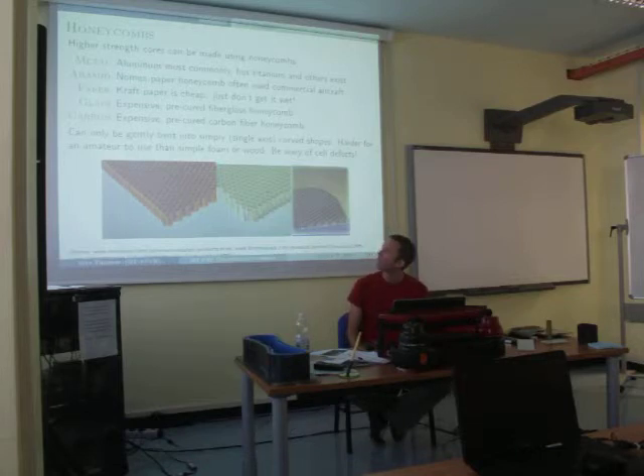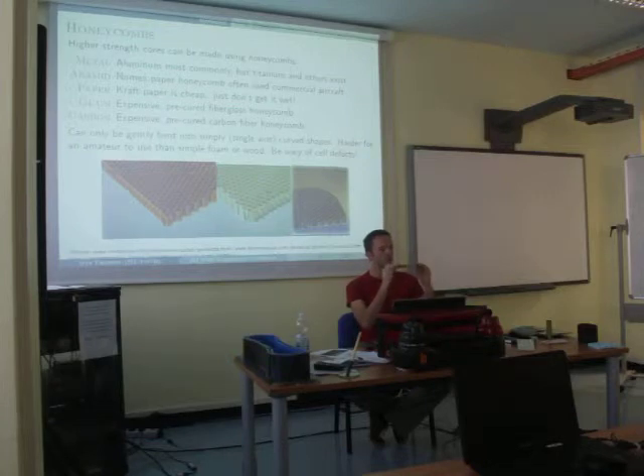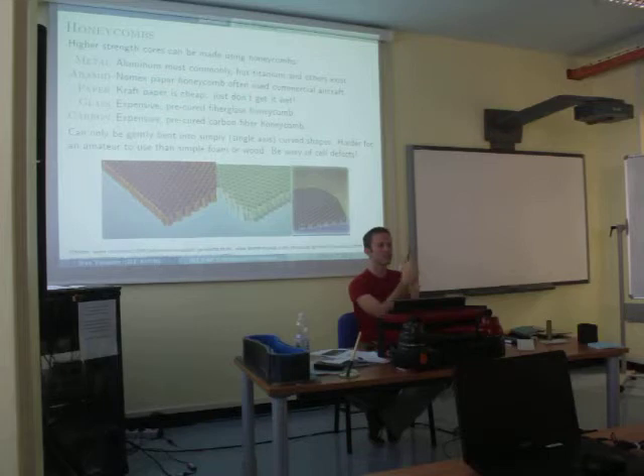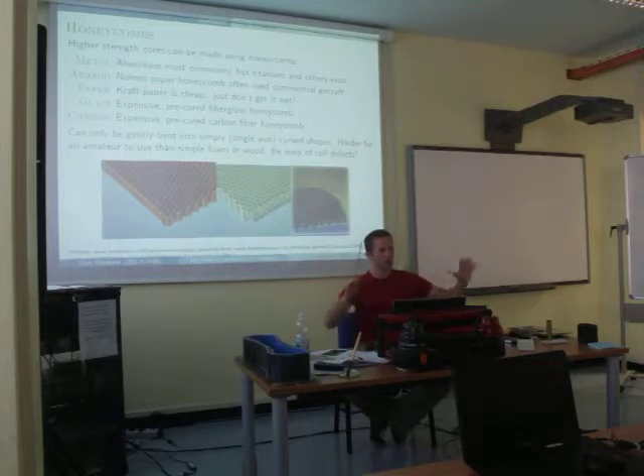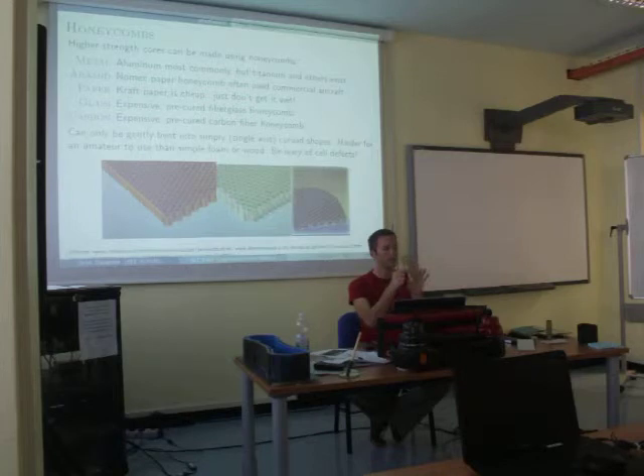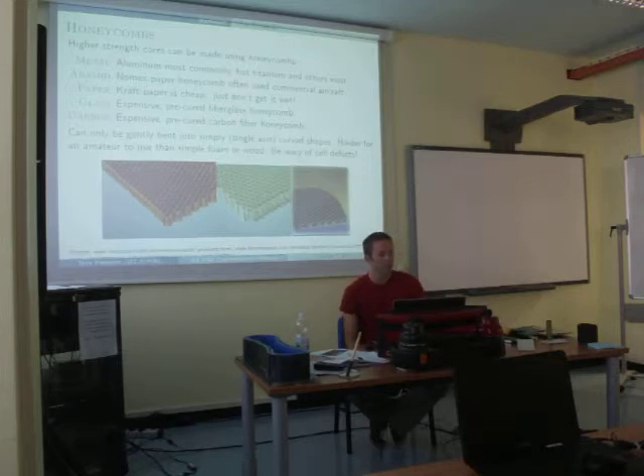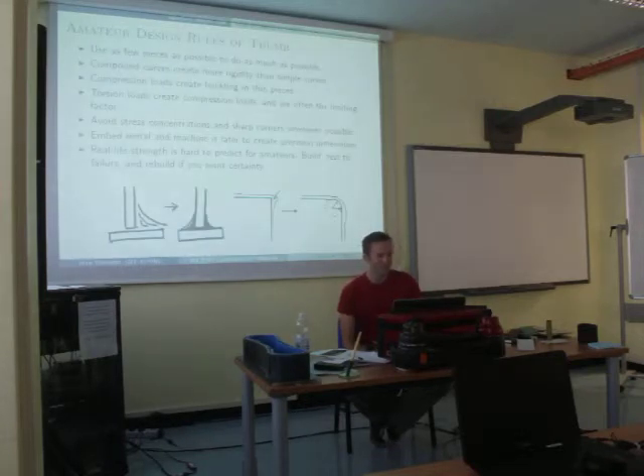You can gently bend these honeycomb structures along a single curve, but you can't do a double curve. You can't bend it on this axis and that axis at the same time. So it's more difficult. You can't really use this except for very, very large compound curved surfaces. Also be wary of cell defects. Sometimes, the way the honeycomb is produced, it will have lines of improperly made cells, and those can become very weak in practice. It's like when you're making glass, the glass fibers have fewer imperfections, and the smaller your piece of honeycomb, the smaller your imperfections are going to be. You're less likely to run into them.